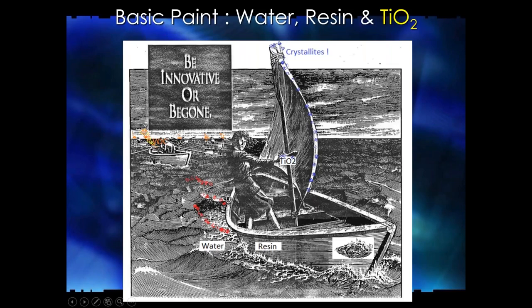And then we have the new technology. And what you see over here is some sort of mysterious red material that's coming out of the new technology. And that's surfactants. And the reason why is because the resin itself, off the bow of the boat, has a lot of water. And so the resin solids had to drop in order to make the resin particle size smaller so that during the coalescence, the particles will, by capillary forces, form a film.